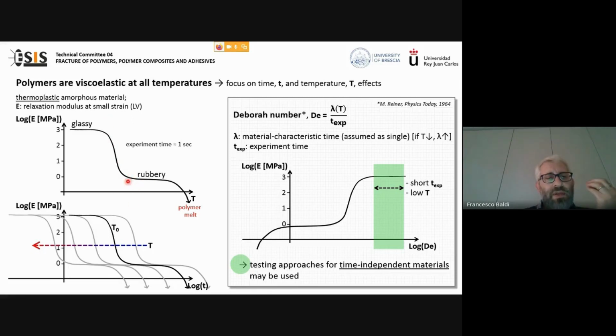But it is interesting to observe that if I plot the modulus, the relaxation modulus, as a function of the time for which I am observing the mechanical response of the material, that is practically a time of experiment, and I keep the temperature fixed, for example, to 0, I can observe a similar transition. Now, the combined action of temperature and time of experiment, the viscoelastic response of a viscoelastic material, of course, was described by referring to a dimensionless number, that is the Deborah number.